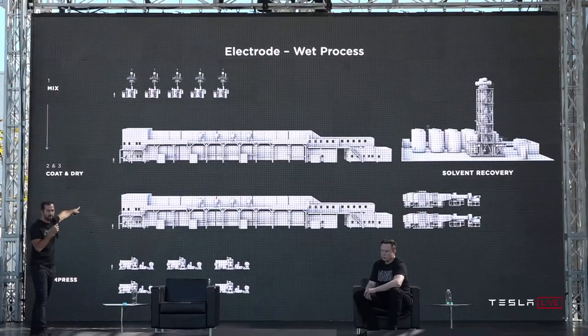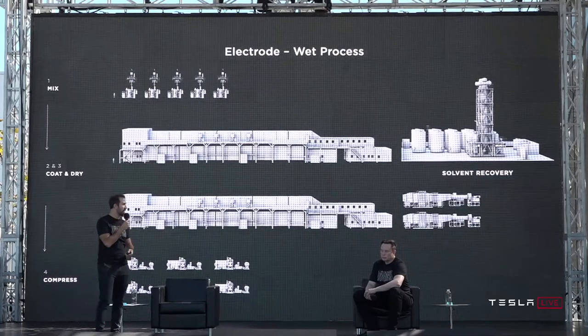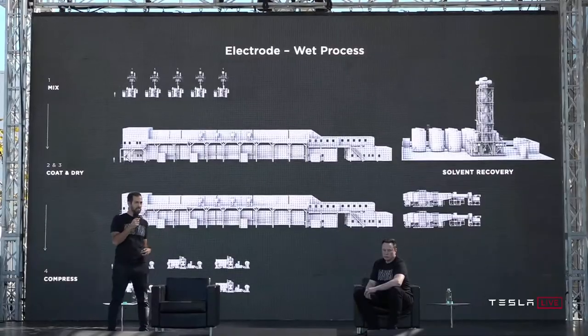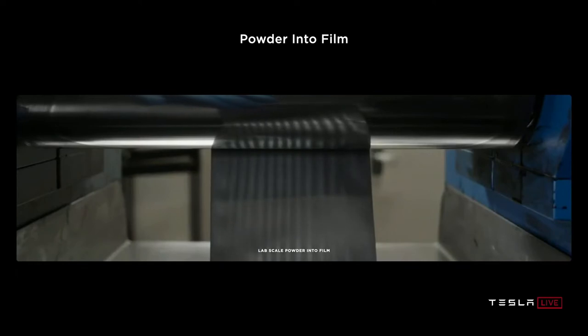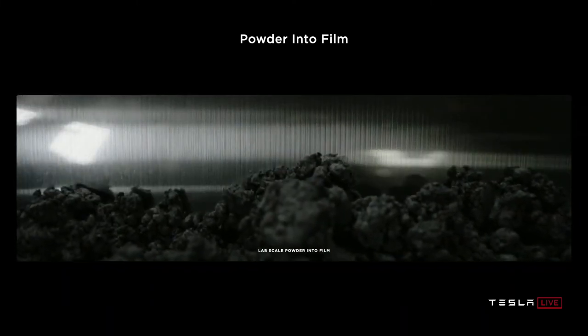Normally, to produce a battery you have to create this slurry, coat it on the battery jelly roll, and then bake it — it's a long, expensive process. So Tesla, after acquiring Maxwell, has worked on improving this dry electrode process. Now they can essentially take a powder and press it down into a film to create the electrode on the battery. Tesla claims they can reduce the cost per kilowatt hour of their batteries by about 18%, hopefully also reducing the cost of their vehicles in the future.